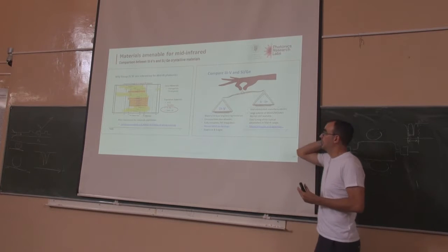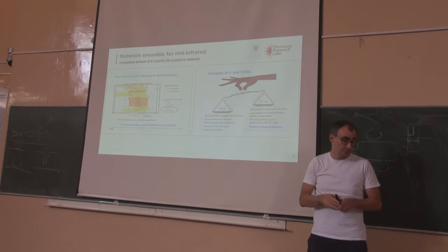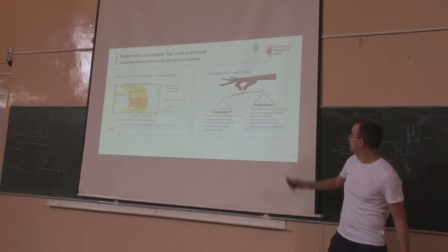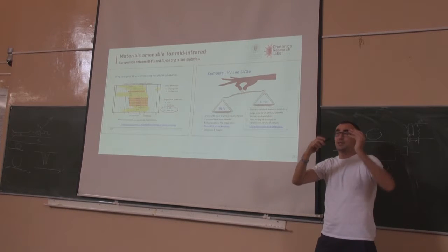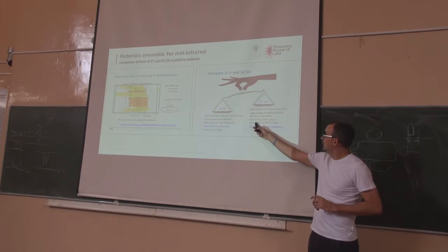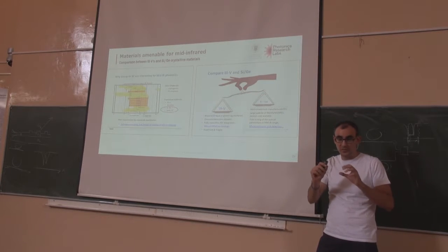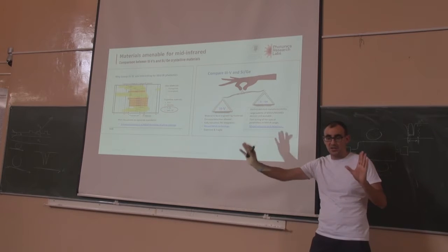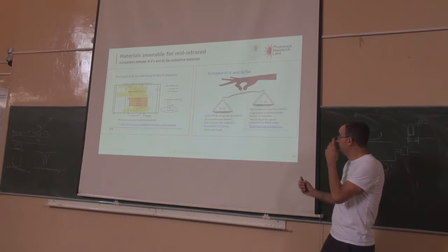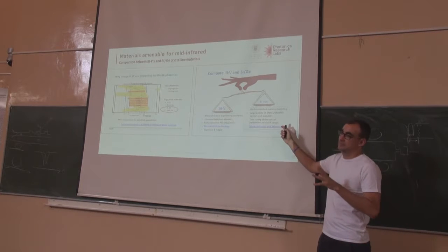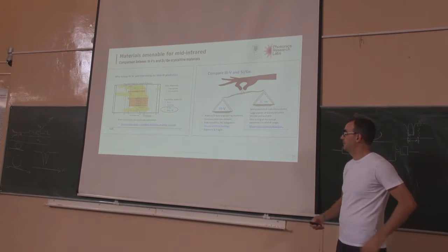very well known, okay? But on the other hand, silicon and germanium are well established because they are used to make electronics. And now they can also do microelectromechanical systems, which for making switches is really nice. What you can do with these materials is fine-tune the combinations to make them widely transparent in the mid-infrared, something that you cannot do, for instance, with the 3-5s. But they don't have emission and detection in the mid-infrared, okay? Detection they have with germanium in the near-infrared.